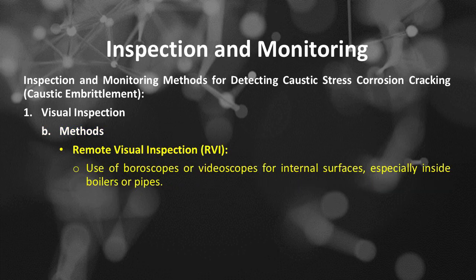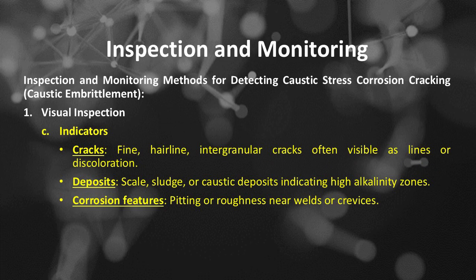And the second visual inspection method is remote visual inspection or RVI, use of borescopes or videoscopes for internal surfaces, especially inside boilers or pipes. Indicators of damage when performing visual inspection include cracks, fine, hairline, intergranular cracks often visible as lines or discoloration; deposits, scale, sludge, or caustic deposits indicating high alkalinity zones; corrosion features, pitting or roughness near welds or crevices.